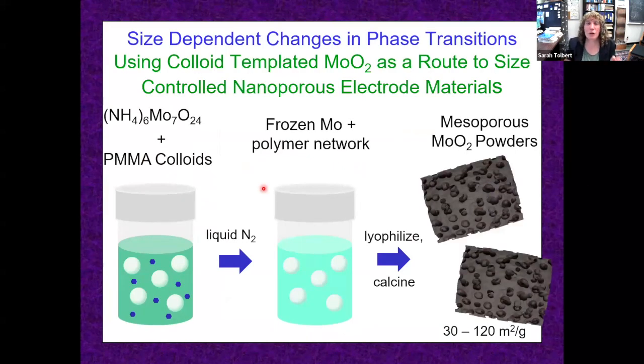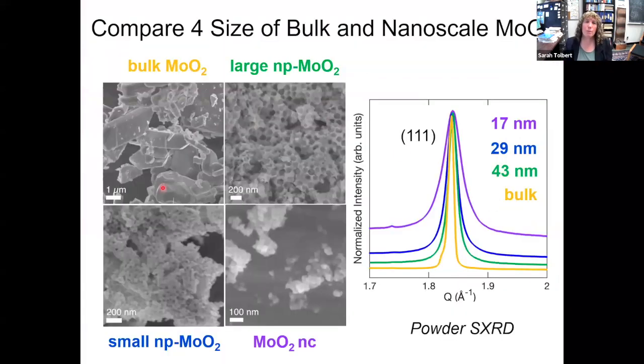So we want to make materials with different sizes. And the way we do that is we mix together a little cluster called a polyoxometallate cluster that contains our molybdenum and little tiny spheres of plexiglass that we made in our colloidal mayonnaise synthesis. And then we want to dry them, but we don't want them to demix. So we freeze dry them, just like freeze-dried fruit. We dunk them in liquid nitrogen, and then we use vacuum to pull off the water. And we keep mixed inorganic and organic components. And we can use this to make really beautiful porous powders. So we're going to use 4 samples here: bulk moly oxide, a large porous material that has 50 to 100 nanometer pores, a small porous material that has 20 or 30 nanometer pores, and then nanocrystals that are only 10 or 20 nanometers in diameter.